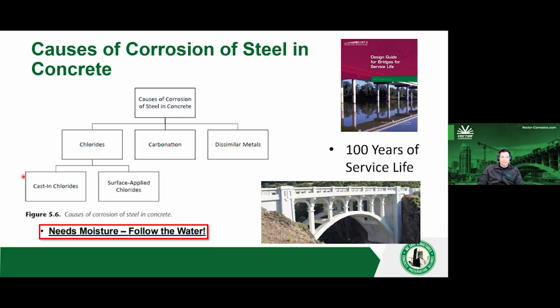Now I have this flow chart. It comes from a document from the TRB, Transportation Research Board. It's called the SHRP 2 project. It refers to bridges specifically, about getting their design life to 100 years plus, repairs to 100 years plus. The concepts from the corrosion section, which is very thorough, apply to all structures, including parking ramps and parking garages. So that's why I included it here. The causes of corrosion of steel in concrete: chlorides, carbonation, dissimilar metals. Chlorides could be either cast in, maybe you have an accelerant, maybe you have an aggregate that's chloride contaminated, and corrosion can initiate and break down the passivation layer.